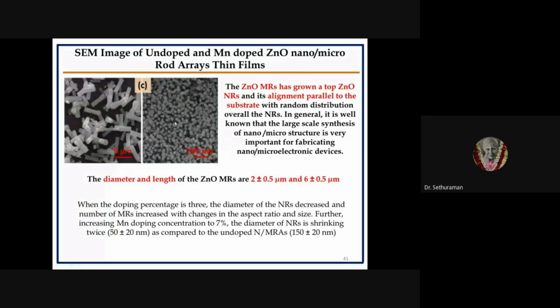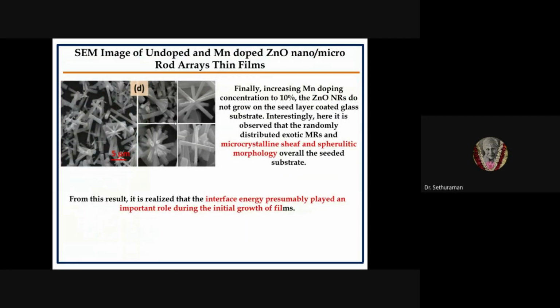So when the doping percentage is 3, the diameter of the nanorod is decreased and the number of microrods is increased, with changes in the aspect ratio and size. But when the Mn doping is increased to 7, we found that the nanorod diameter is shrinking twice, to about 50 nanometer as compared to the undoped one. The undoped one is higher, and the doped one is lower with increasing doping percentage. Finally, the Mn doping concentration is increased to 10%.